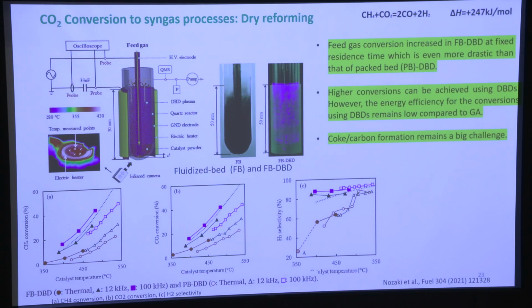To summarize, the fluidized bed is much better than the fixed bed in terms of dry reforming. And high conversion can be achieved using DBD, but however, the energy efficiency is bad, because a lot of carbon formation remains a big challenge.